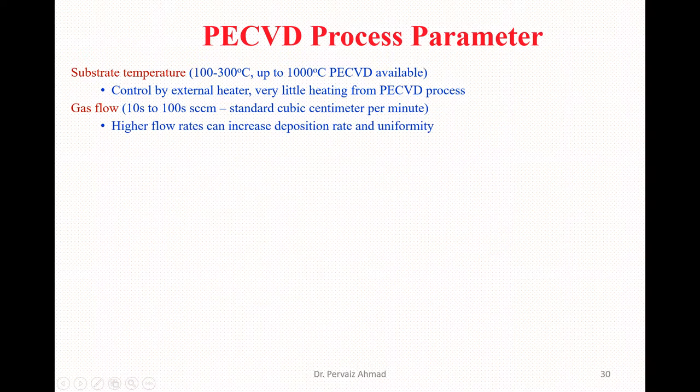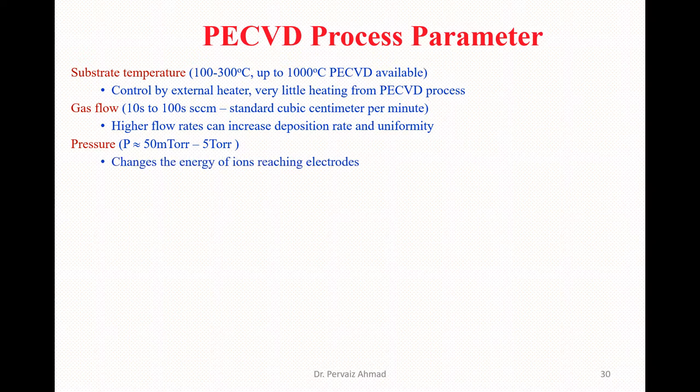Higher flow rates can increase deposition rate and uniformity. If we increase the gas flow, it can increase the deposition rate and uniformity of the thin film. Pressure in this particular technique ranges from 50 millitorr to 5 torr.